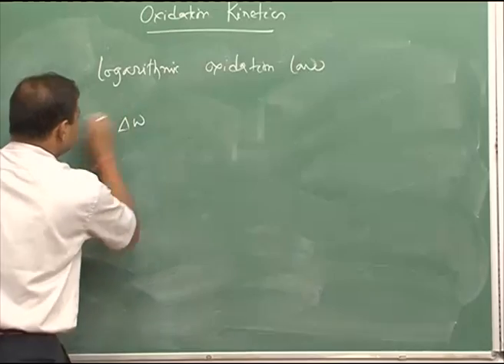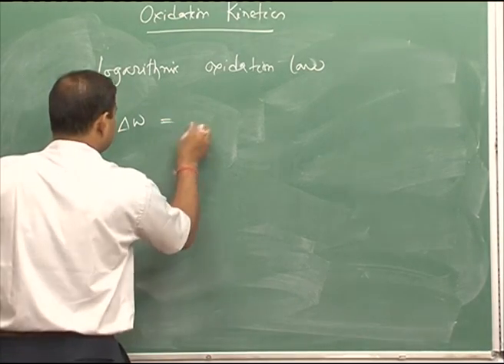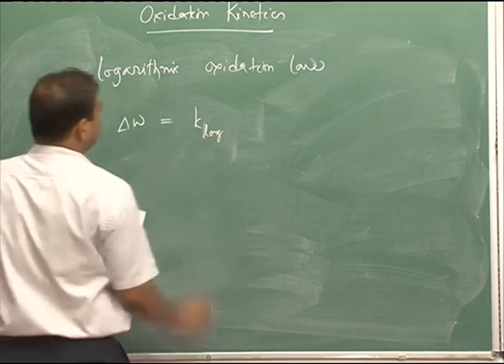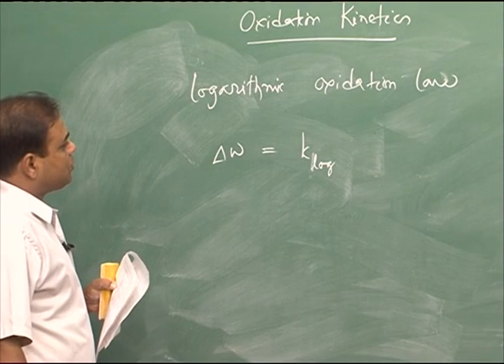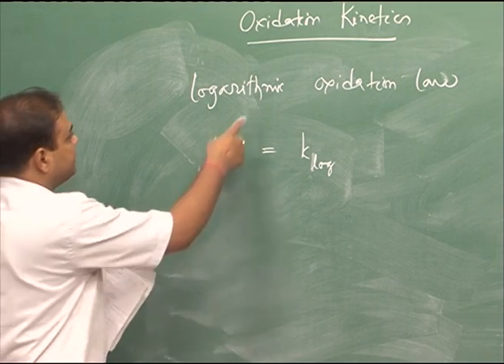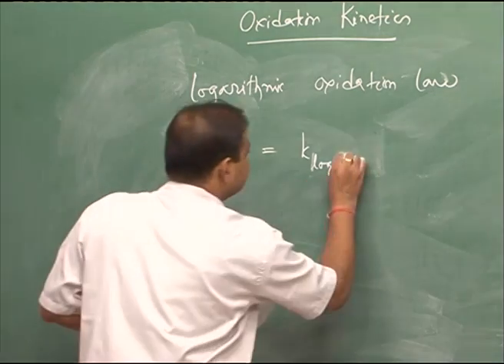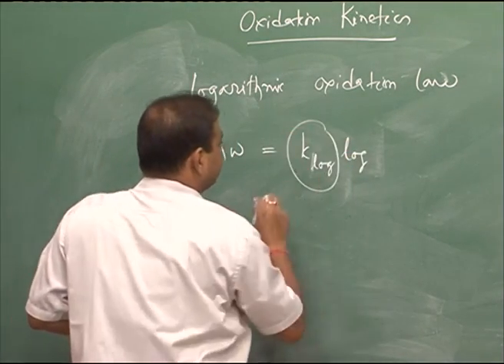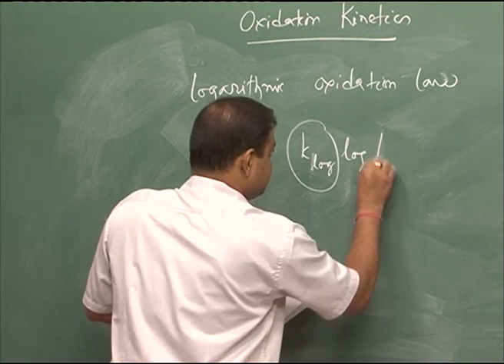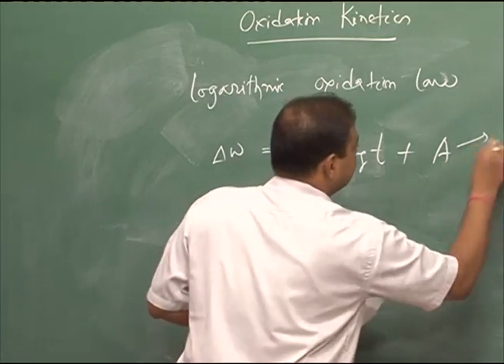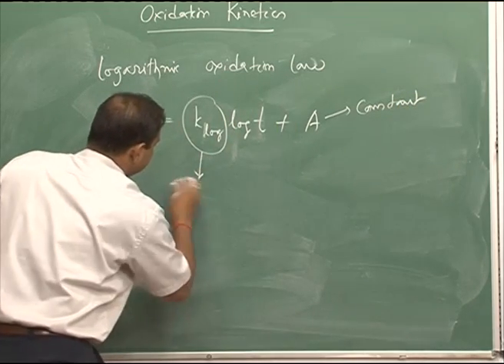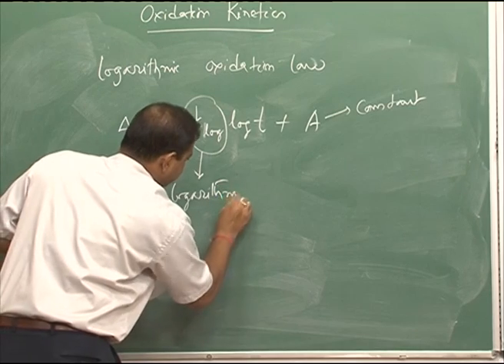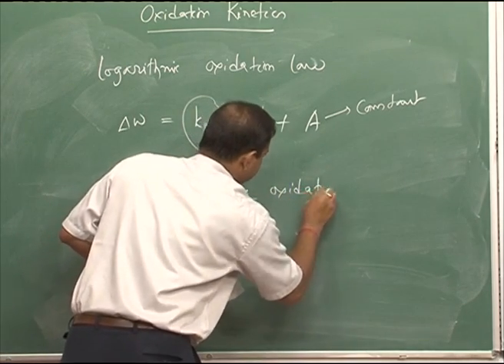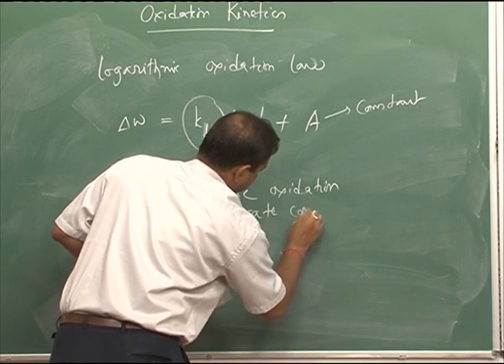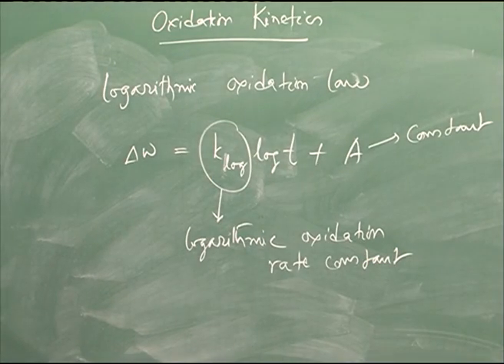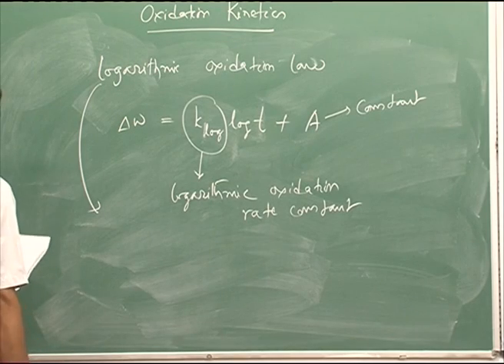where del W, which is the weight gain per unit area, would be equal to K log t plus A. K log means the rate constant when the oxidation is following a logarithmic law, which is basically the rate constant for the oxidation process, and this A is a constant.